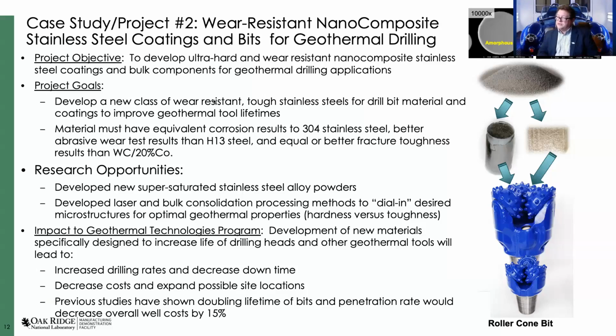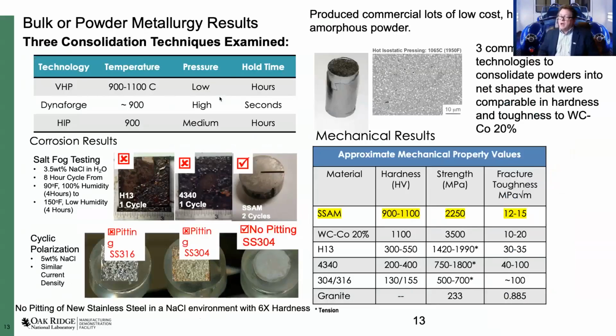While the monolithic material systems are very interesting, where I believe the biggest impacts are is in looking at graded structures, depositing these within steels, and showing very wear-resistant surfaces. These are some of the results from this project, where we showed that compared to stainless steels, when we started doing cyclic polarization tests, one of the really amazing things, because of the fine microstructure, is that you actually don't get pitting. So we're not getting the localized pitting corrosion that occurs in a lot of the stainless steels you use.